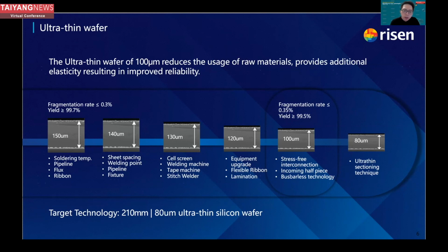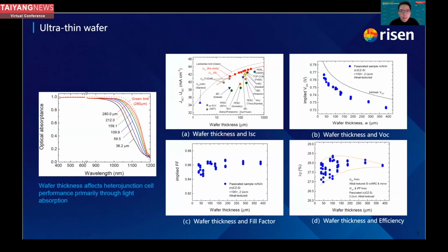During our R&D, we have already reduced the thickness of our wafer from 150 to 100 micrometers. Maybe there is some wonder or doubt about whether thinning the wafer affects the efficiency or reliability of the solar cells and wafers. And through our studies, which are verified from these pictures, on the left you see the relationship between the wafer thickness and the optical observation. And we can see that at wavelengths less than 700 nanometers, the absorption rate was basically the same.